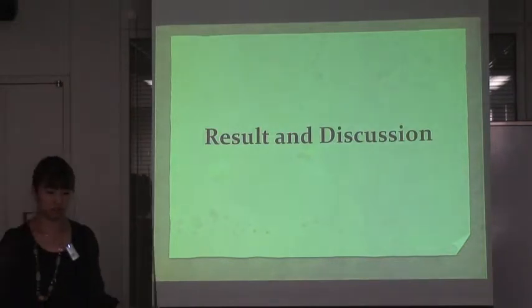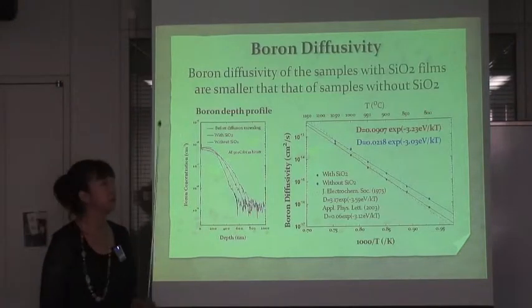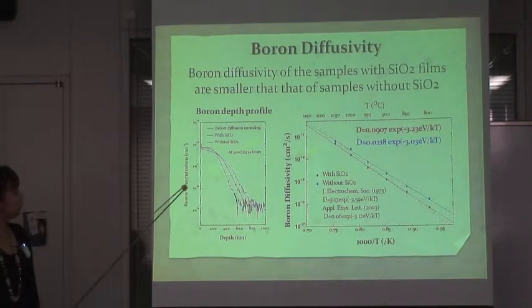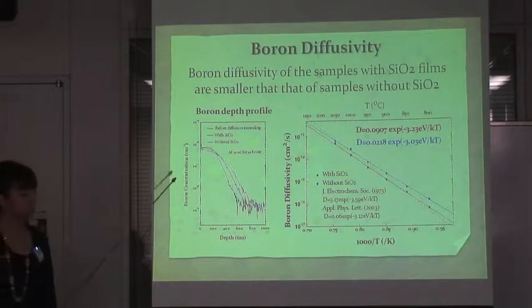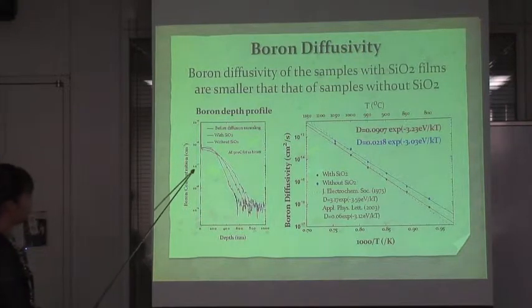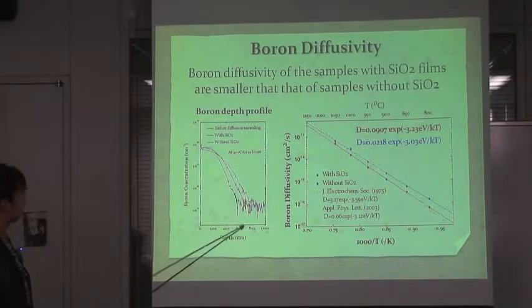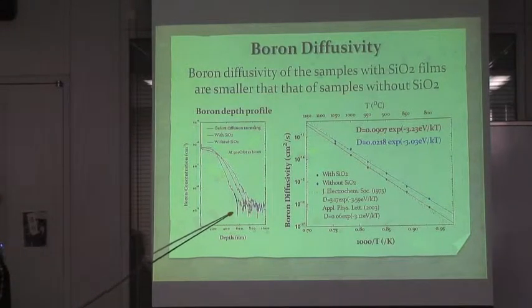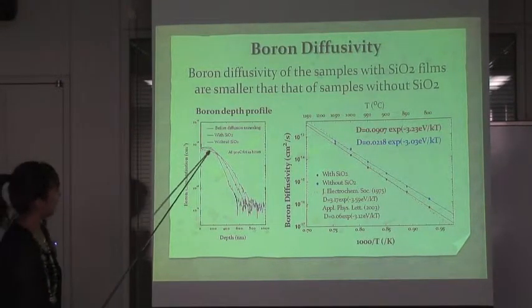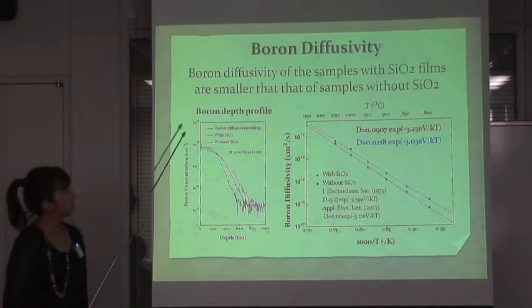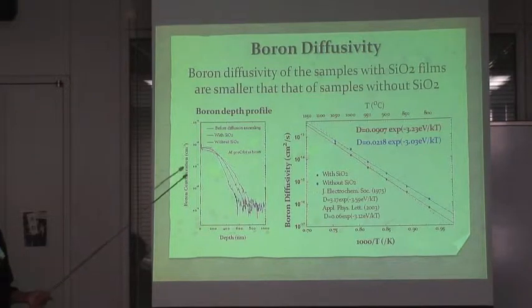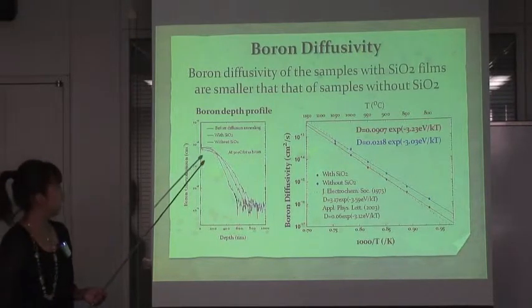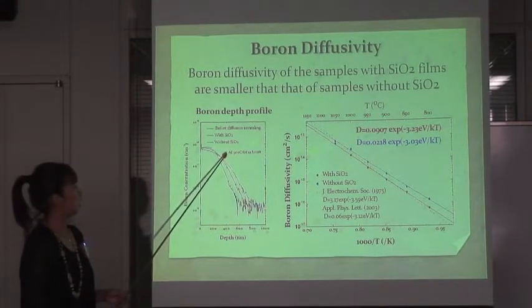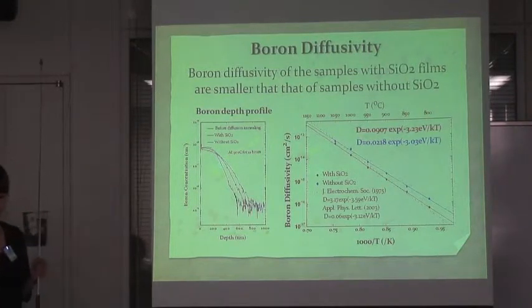So, move on to the results and discussion. Here, this figure shows boron depth profiles before and after diffusion annealing. The y-axis is boron concentration and the x-axis is depth. And the black line is the profile before diffusion annealing. And the red and blue lines were the profiles after diffusion annealing of the sample with silicon dioxide and without silicon dioxide, respectively. Anneal is done at 900 Celsius degrees for 12 hours.